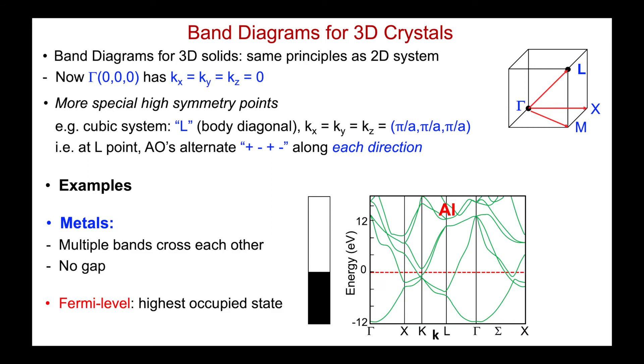So here's the band diagram for aluminum metal. Now we know what some of these points mean. Let's not worry about some of the letters that we haven't seen. They're just different directions. And they're going to get more complicated, of course, if the system isn't cubic. If it's hexagonal or other lower symmetries, things get tricky. Here are my spaghettis hanging on the k points. Immediately we see there's no gaps. Multiple bands are crossing each other, all over the place. We can start to see some bands are running downhill, some bands are running uphill. Maybe we could go into more detail and think about whether those are s-derived or p-derived or whatever. We won't do that here. The main point is if I see a diagram like this, and typically the Fermi level is shown on it, here at 0 eV as it turns out, I can tell straight away that's a metal. There's no gap. And there's my corresponding box picture.